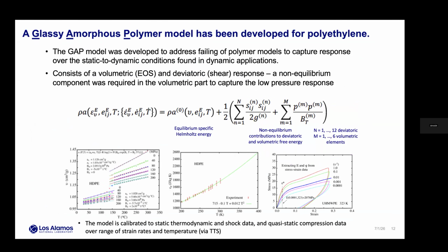I mentioned that we have a glassy amorphous polymer model that we're using at Los Alamos. It's been implemented into Abaqus, and then it's been implemented into CTH. But as I mentioned, that model basically is broken into two components. It has an equilibrium portion, which is volumetric. It's actually somewhat based on, in our case, a very simple form.